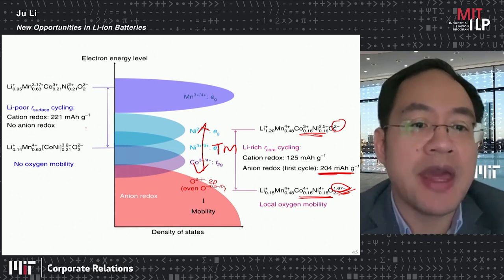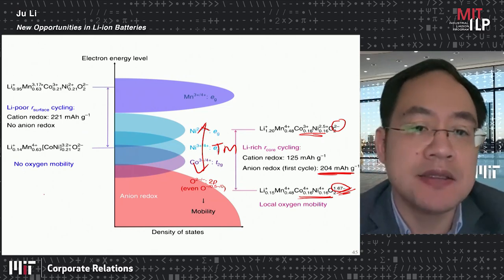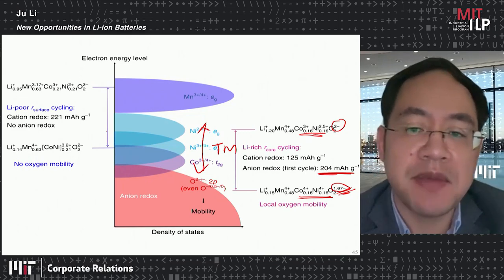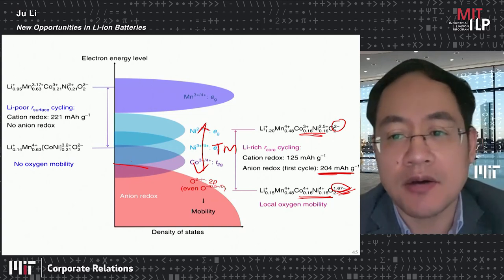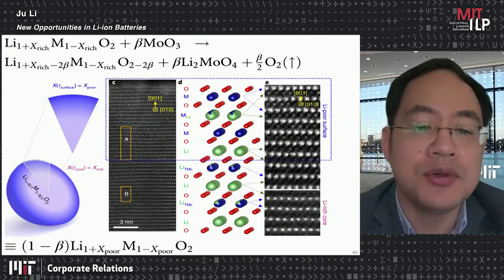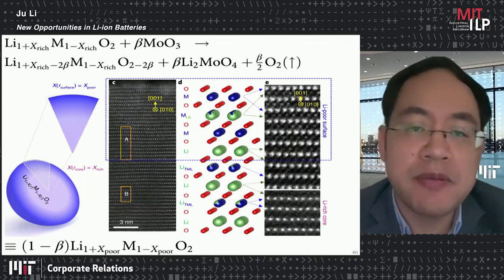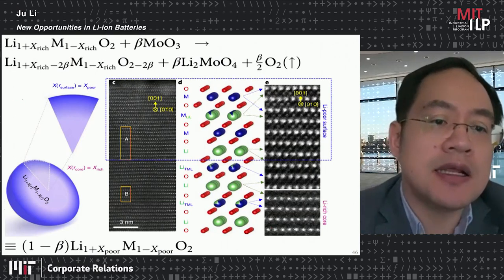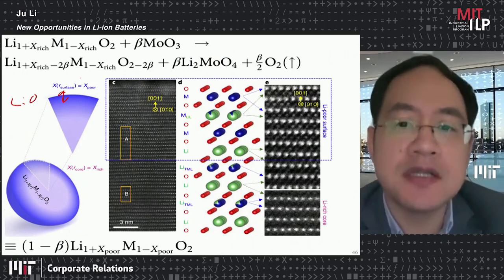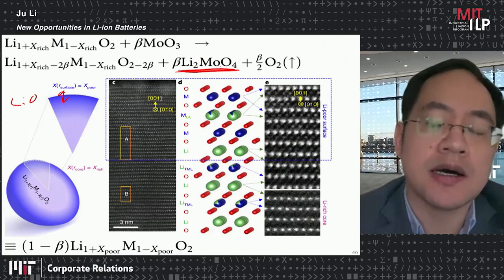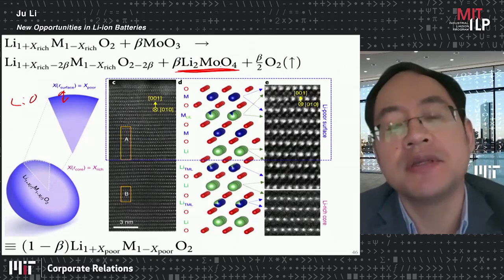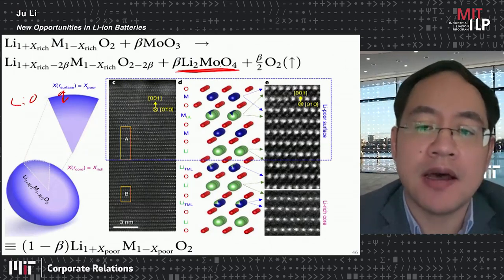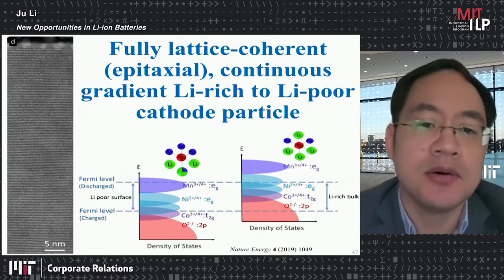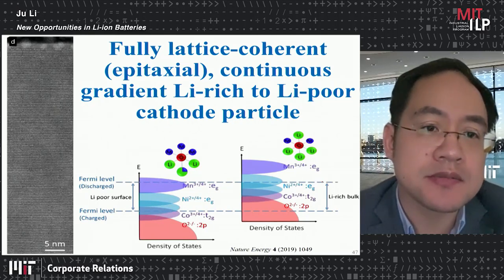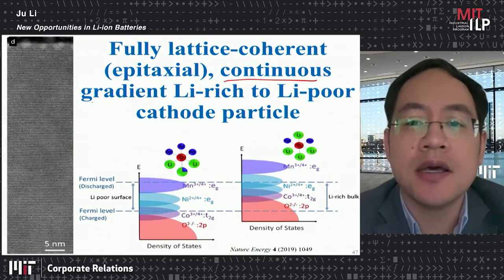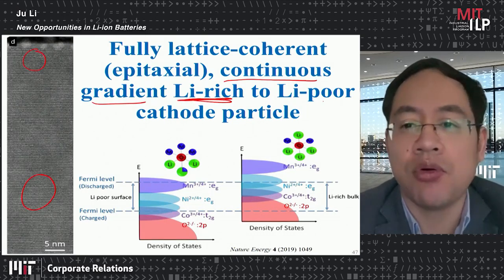Whereas on the surface, because we have this transition metal replacing the lithium, we elevate the Fermi energy and make sure it does not touch the oxygen band. So the way we do that is we use a molten oxide, the molybdenum oxide, and that basically sucks out lithium molybdate from the surface. And furthermore, this reaction product is also completely wetting the surface, even goes to grain boundaries, and it's also water soluble. So you just wash it, and then your secondary particle breaks up into these standalone 200 nanometer primary particles. So we can have this continuous gradient from this richness inside to this poorness on the surface.